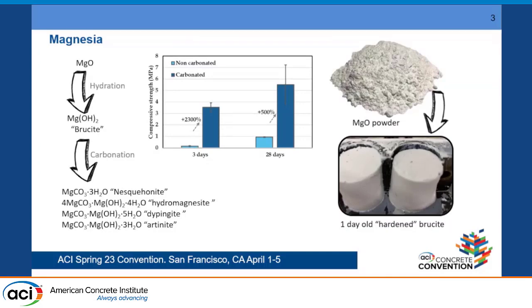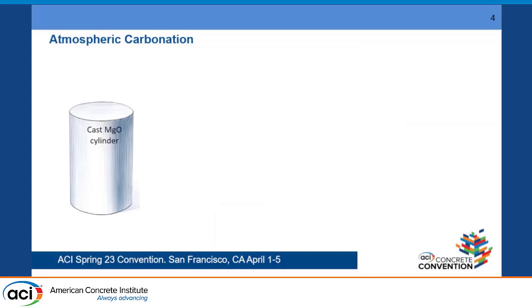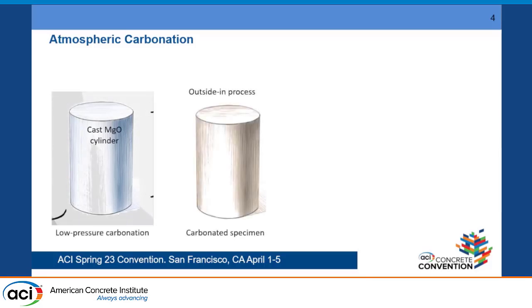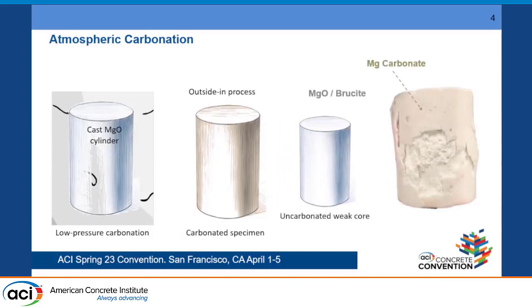Now, the physical strength it gains when it's carbonated and cast is still not high enough to use it as a construction material. But that's where the idea of using 3D printing comes from. If we look at atmospheric carbonation of a cast specimen, we typically place it in a low pressure, high carbon content chamber, and that would start to carbonate the sample. But because carbonation is an outside-in process, which means carbon has to go from the outside of the specimen and penetrate through, we would not be able to fully carbonate it. So what we would end up with is a carbonated shell with an uncarbonated weak core, and that's why we see the low compressive strength.